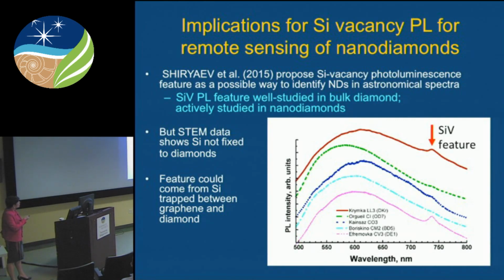And a group out of Russia, Shiryaev and co-workers, proposed that the silicon vacancy luminescence feature they were seeing in the nanodiamond residues was intrinsic and could be used as a way to go out and make astronomical observations of nanodiamonds in space. But what the STEM data that we took shows is, in fact, the silicon atoms are diffusing rapidly over the surface of the materials and probably are mostly simply products of the acid dissolution or so on.